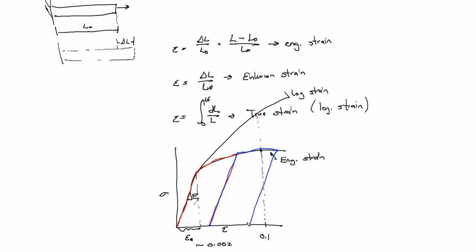In reality, when you do large deformation samples on rocks, it's real hard to even see the initial elastic response, because what happens when you initially load a rock is, just like I said, you know, there's a lot of micro cracks and flaws in there, and some of those can be open and other things, and so the first thing you do is you just sort of close up all the flaws